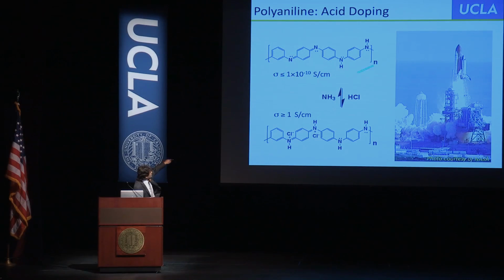Well, I told him we have this conjugated polymer, and it's an insulator, 10 to the minus 10 Siemens per centimeter. But if it sees hydrochloric acid, it has over 10 orders of magnitude change in conductivity, which is just absolutely huge. So he's like, great, send me some. So I sent him some, and 3 weeks later he called me and said, well, I got good news and bad news. So I said, well, start with the good news. He said, well, the good news is it works. I said, well, then what's the bad news? He said, well, it's slow.